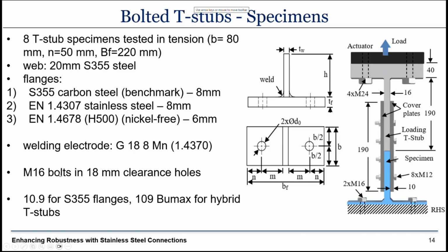And in all cases, we used M16 bolts in 18 mm clearance holes. We used high strength bolts, either 10.9 for the carbon steel specimens or 109 Bumax for the hybrid T-stubs, which is an equivalent bolt grade to the high strength carbon steel bolt grade.